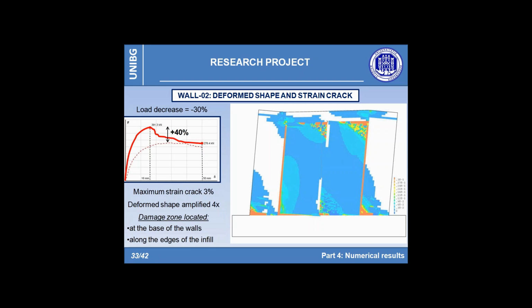Observing the figure, it can be seen how at the base the cracked area is extending in height due to the presence of an inclined strut that develops within the infill. Regarding the outer frame, a crack pattern not dissimilar from the previous one can be recognized, except for the damage zone affecting the right shear wall due to the contribution of the compressive struts.